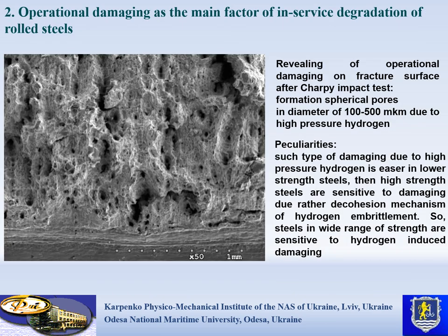Operational damage is the main factor of in-service degradation of rolled steels. On this slide, you can see operational damage on the fracture surface after a Charpy impact test. Formation of rows of big circular pores in the rolling direction, evidently due to high pressure hydrogen. This process should be easy in low strength steels, while high strength steels are sensitive to damage due rather to the decohesion mechanism of hydrogen embrittlement. So, steels in a wide range of strengths can be sensitive to hydrogen-induced damage, but due to different mechanisms.